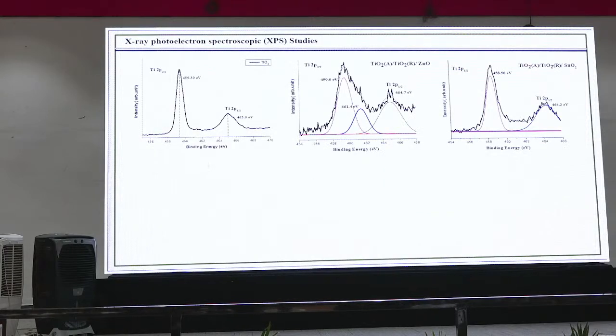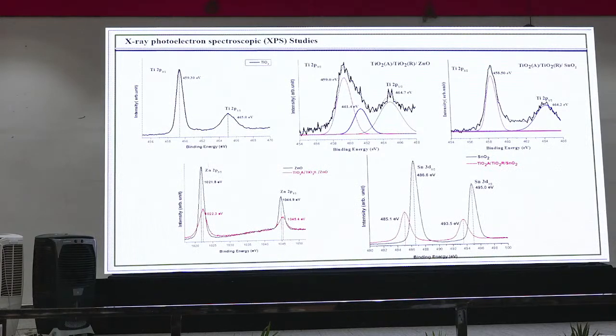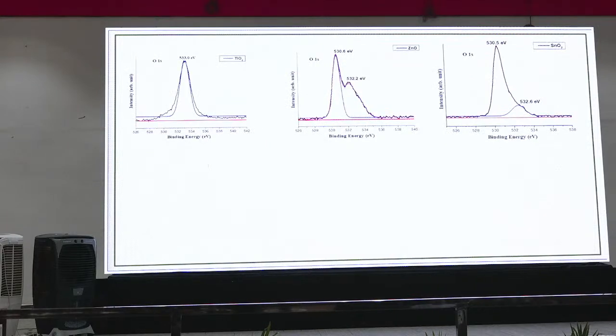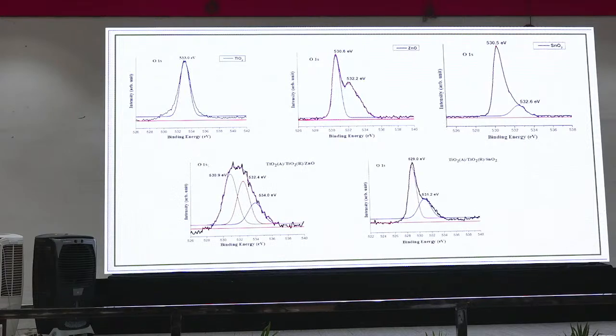Then we did the XPS studies to see what exactly is on the surface. From the XPS studies, we understand there is an interlink between the titanium and the zinc, and they are partially shifted. Based on the shift, we are able to know from where to where the electron transfer is happening on the surface, because photocatalysis happens most prominently on the surface. Then we tested for oxygen, to see how many different kinds of chemical composition we have. There will be pure composition in TiO2, ZnO and SnO2, but when we have done the heterojunction or ternary junction, that chemical composition has been mixed with many varieties of subcomposites. It is not a pure chemical nature. Instead, we have a different chemical nature.